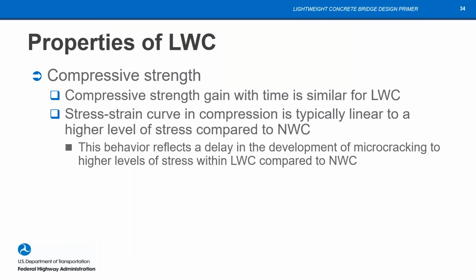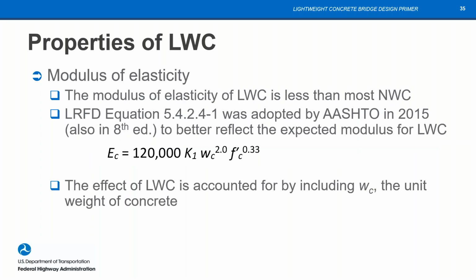As far as compressive strength, the strength gain with time is similar for lightweight, and the stress strain curve is typically linear, a little further up than normal weight, but we haven't really quantified that very much. As far as modulus of elasticity, the lightweight concrete is less stiff than most normal weight concretes. There's an equation in the code that came in 2015 that's better calibrated for higher strengths as well as for lightweight concrete.